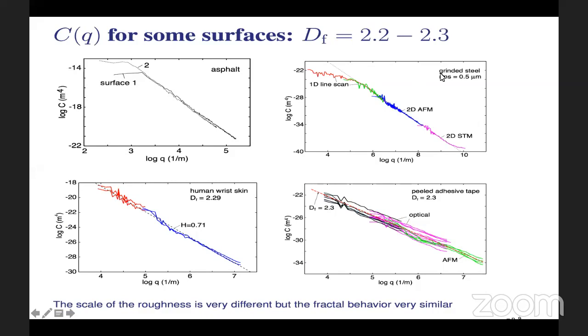For example, for grinded steel, you can measure your surface roughness with different instruments. Here it was done by 1D line scan, 2D AFM, and 2D scanning tunneling microscopy, but then they overlap with each other to form a complete power spectrum ranging from a centimeter to a nanometer. Depending on the length scale you're interested in, you can use different techniques to characterize your surface. The surface roughness power spectrum is very important to characterize the surface roughness of your materials. It has all the information that is needed for doing contact mechanical calculations and related predictions.